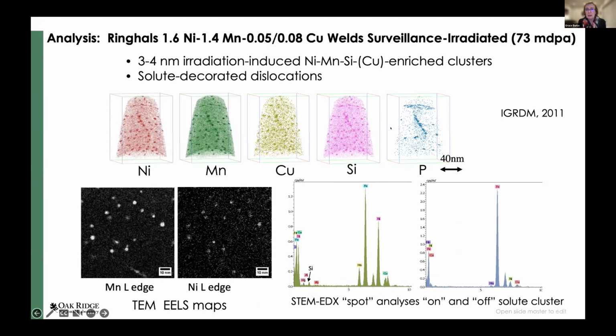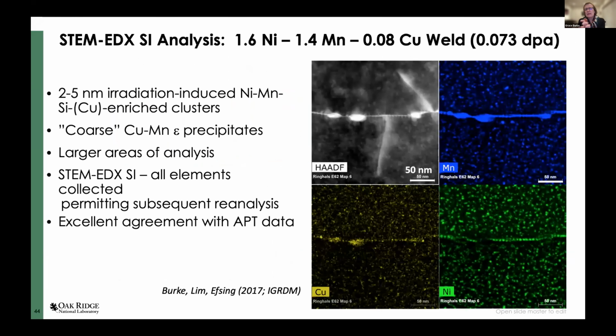And we can extend that looking at various welds and things. So what we could do only with atom probe tomography. Here's an EELS map from the Titan, and we can see our manganese L-edge, our nickel L-edge. Nickel looks pretty diffuse, but I would just say that if we swap this with STEM EDX, our manganese would look diffuse and our nickel would look strong just because of background subtraction. And again, don't forget the value of some discrete spot analyses, because going on to one of our clusters, we can pick up the silicon, the manganese, and the nickel very clearly, and moving just off it, they're gone. And again, the fact that we can sample larger regions, we can look at variability. So it's really amazing, an excellent agreement with atom probe data.